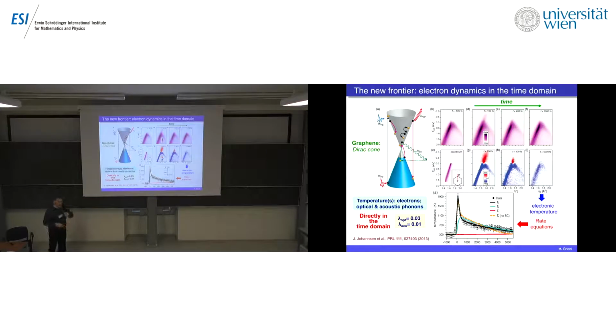And this is in pump-probe experiments, ultra-fast experiments, where one hits the material with an ultra-short laser pulse, then excites the material and sees the relaxation by sending a second pulse and extracting the photoelectrons. So this is an example for graphene. You have here the spectra before the pump arrives, and here just immediately after the arrival of the pump, you see probably there is some extra electrons over here. The difference spectra are clearer, where you see red is added electrons. These electrons go into the unoccupied part of the Dirac cone, and then progressively the system relaxes.